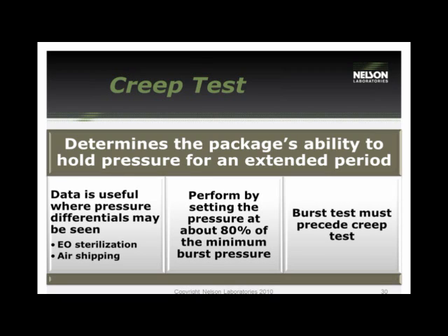So when you're doing EO sterilization and vacuums are pulled and things like that, or possibly air shipping, travel over mountains where you change in elevation, this data will help you identify where these pressures can be issues. The process for the test involves setting the pressure at 80% of the minimum burst test. So you have to perform the burst test first and then determine what that 80% average is in order to move forward with the creep test.